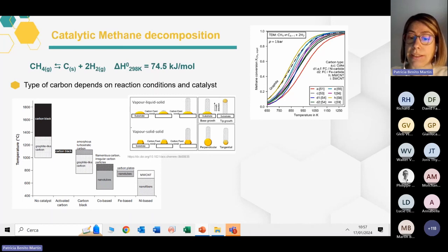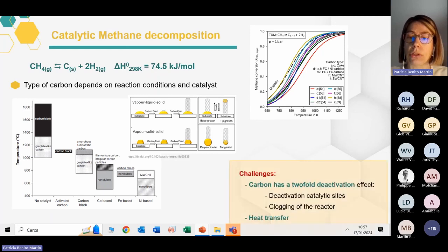But as already anticipated in some of the early presentations, producing a solid or generating carbon is the reaction that we always want to avoid when producing hydrogen from steam reforming, because carbon has a twofold deactivation effect. It will deactivate the catalytic sites and it will clog the reactor. Moreover, this reaction is less endothermic than steam methane reforming, but still we need to reach high temperatures to achieve a high conversion and in turn a high hydrogen productivity. So we will also have to deal with the heat transfer.